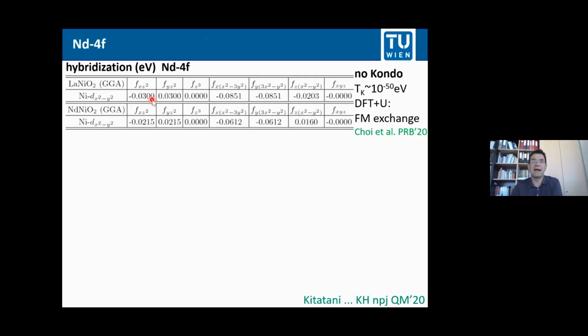So here we have calculated the hybridization of the neodymium 4f with the x squared minus y squared, which is there to stay. And it's very small, it's 30 meV. You have to take this hybridization squared, divide by U, and then take the exponential to calculate the Kondo temperature, and it turns out it's 10 to the minus 50. So there will be no Kondo effect with this neodymium 4f.